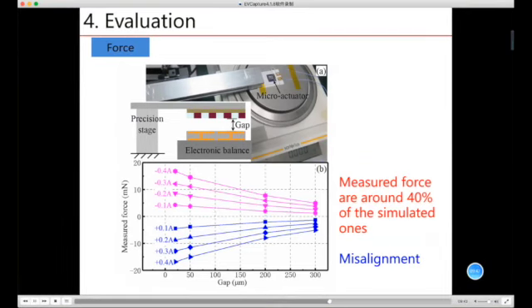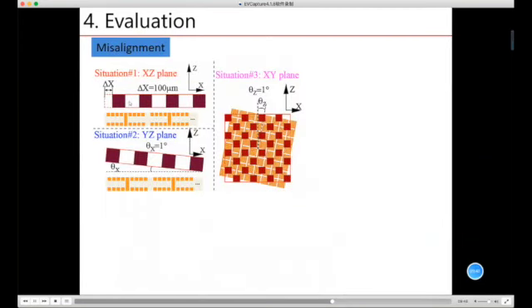This may be caused by the misalignment effect, which is demonstrated here. It means that the stator and the mover are not aligned in different directions. The force will degrade. We analyze the misalignment in different situations. Situation 1 is the misalignment in X translational freedom, and situation 2 is the misalignment in the X rotational. And situation 3 is the misalignment in the Z directional axis.